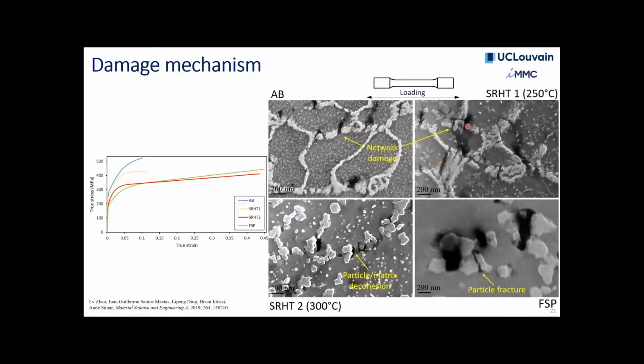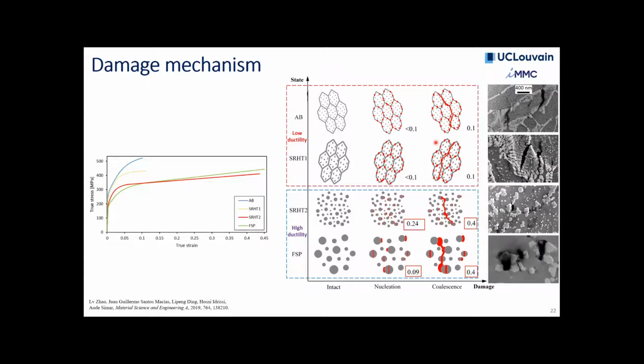This is looking at a failed sample. Same for here, while here you have particle matrix decohesions. Sometimes you do have particle fracture as well, but mainly decohesion of the particle. So here we have a disconnected network, and here we have a connected network. So now if we're looking at the damage mechanism that I'm going to show you in some more detail after, what you can see here is that nucleation of damage happens in these as-built and stress relief heat-treated materials, so the highly connected conditions, at a very low strain.